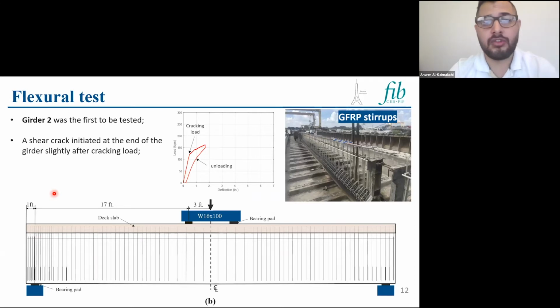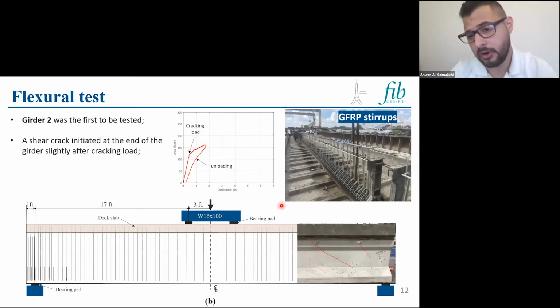Girder 2 was the first one which was tested, and here we can see the shear reinforcement. This is the layout of the reinforcement for girder 2. Those are the GFRP stirrups. So we loaded the girder, and slightly after cracking, we saw a shear crack at the end region, and we decided to unload the girder, because the main objective of this research was to study the flexural behavior of the member, and we didn't want the member to fail in shear.